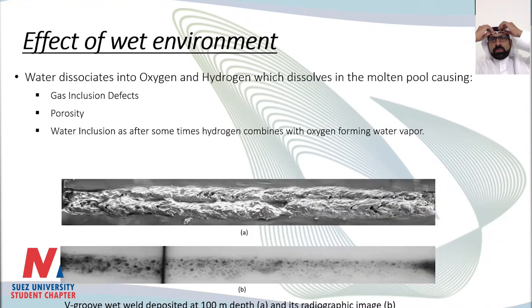Next slide, please. This is a weld I've done at 100 meter depth. As you can see, the first one is the weld. The second picture, figure B, is an X-ray of the bead, and you can see all the small dots here as gas pockets. So it's full of porosity. There is a lot of gas inclusion and water inclusion. If you have gas inclusion, the hydrogen and the oxygen molecules later on will combine and create water inside your weld.